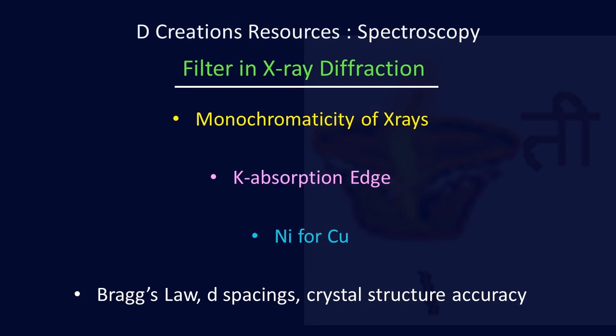So, if there is a polychromatic X-ray beam, then each wavelength in the beam will diffract at slightly different angles and for the same set of crystal planes. So, there would be an XRD pattern in which overlaps of the diffraction peaks can happen. So then it's very difficult to accurately determine the d spacings, and we determine the d spacings to understand more about the crystal structure of the material, whichever is being analyzed. So then it's very complex and challenging for interpretation.